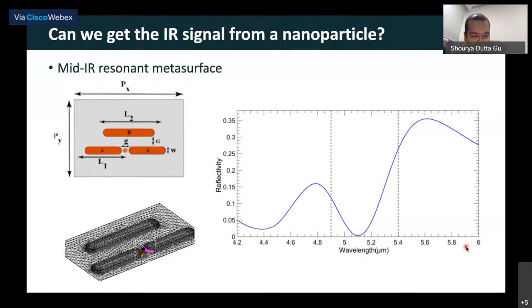So what she did was basically she takes this kind of plasmonic antennas. So each of these bars, labeled A and B, are made up of gold. And then in between these two bars, we have a small gap of around 100 nanometers. Now, this is a typical meshing that we use for doing the numerical simulations. Now, if you look at the response of this structure without this particle, we see something like this. So where the horizontal axis is the wavelength and the vertical axis is the reflectivity, right?